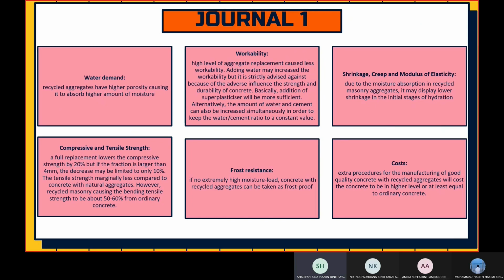The next property is workability. A high level of aggregate replacement caused less workability. Adding water may increase the workability, but it is strictly advised against because of the adverse influence on the strength and durability of concrete. Basically, addition of superplasticizer will be more sufficient. Alternatively, the amount of water and cement can also be increased simultaneously in order to keep the water-cement ratio at a constant value.